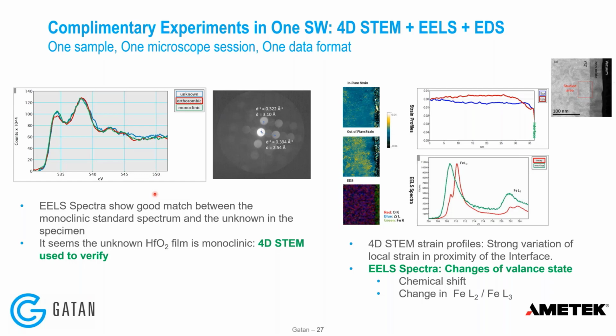You cannot collect EELS spectra and 4D STEM simultaneously because usually the pixelated detector that is used to collect the 4D STEM data is either pre-GIF or post-GIF. And if it's pre-GIF, if you insert it to collect the diffraction images, it's going to block the EELS signal getting to the spectrometer. And if you're doing 4D STEM on the end of the GIF, you're in STEM mode and not in EELS mode. So for 4D STEM and EELS, you have to do them one after the other.